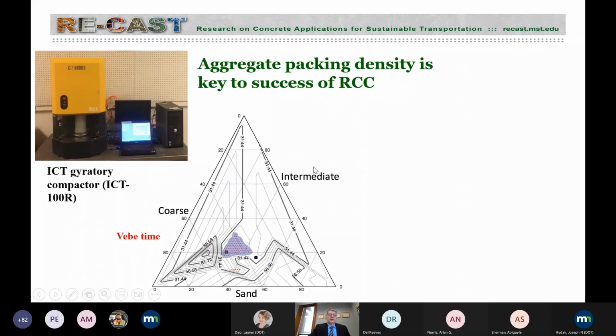And this is some work we did before we worked on the CCP using RCC technology. We could in the lab use an ICT, intensive compaction tester gyratory, that is similar to the one we often use in the asphalt industry. It's a smaller one with a cylinder of 4x8. And we apply a certain protocol of consolidation and determine the maximum packing density.